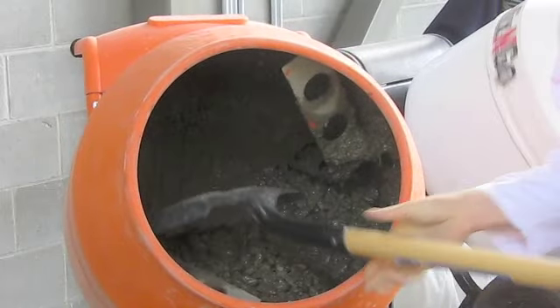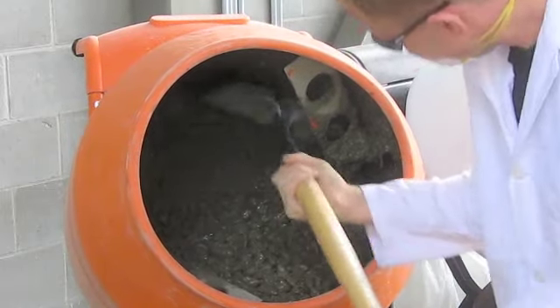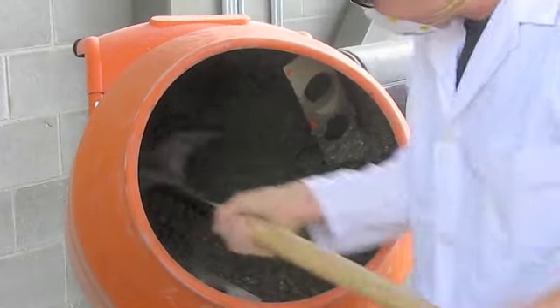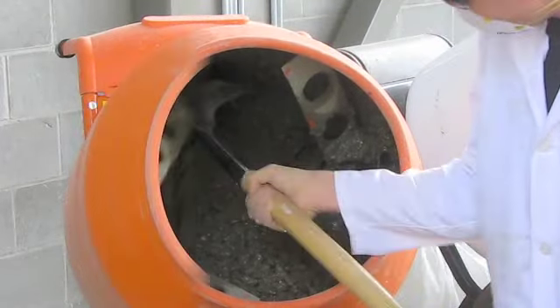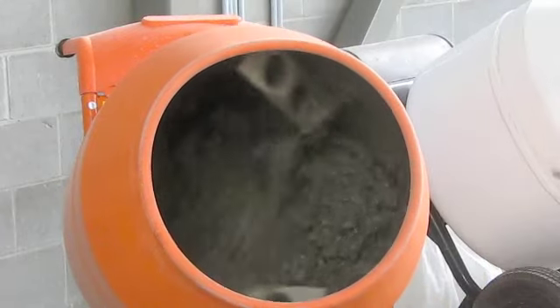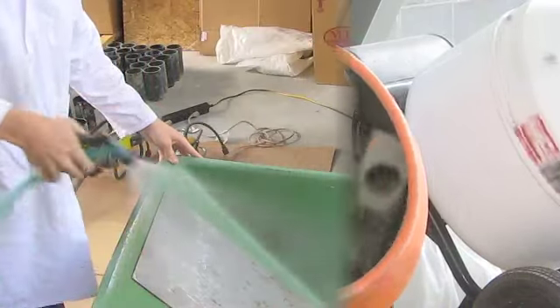After all the materials have been added, you want to make sure you mix thoroughly for 3 minutes non-stop. After 3 minutes and the cement mixer is stopped, you want to scrape off the inside to make sure that you don't have any clumps of unmixed material. After letting it sit for 2 minutes, mix again for another 3.